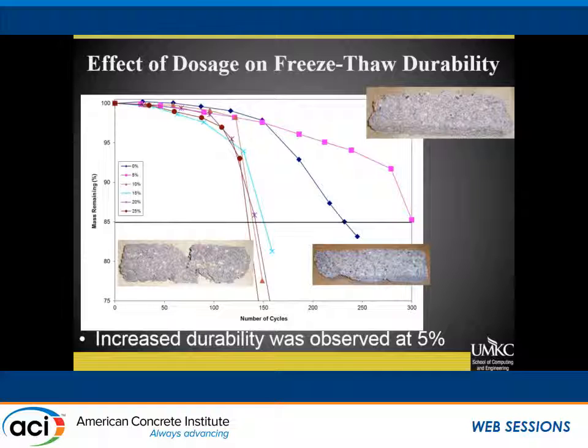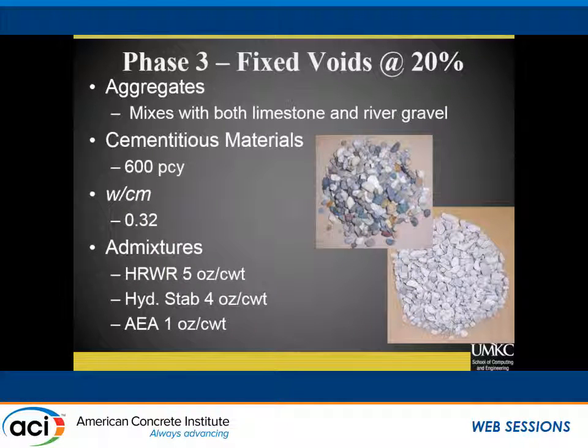Freeze-thaw durability, same samples, we'll run freeze-thaw durability. This was designed to have kind of moderate performance, the control. So our control there, if we're using a mass loss basis, ran to 250 cycles. 5%, because it was a little denser, had better performance. Anything above that dropped off, had similar yet relatively poor performance. So our void content did give us a little bit better freeze-thaw durability. So that was ASTM C666A, the wet, the terrible wet test that we don't like to use, yet we always use. So then the third phase was fixed voids.